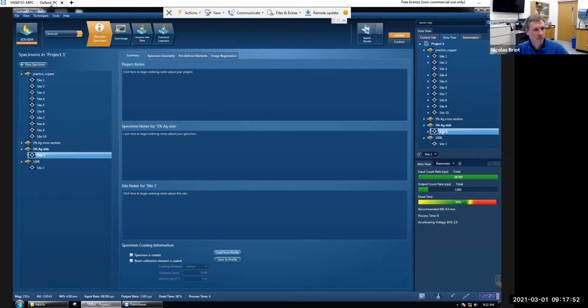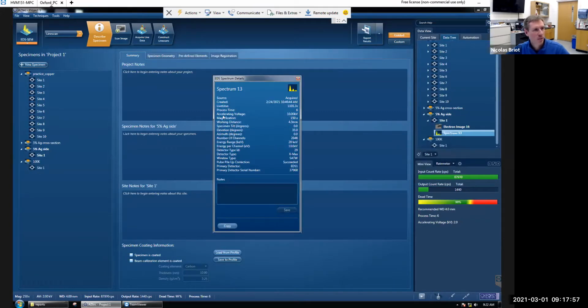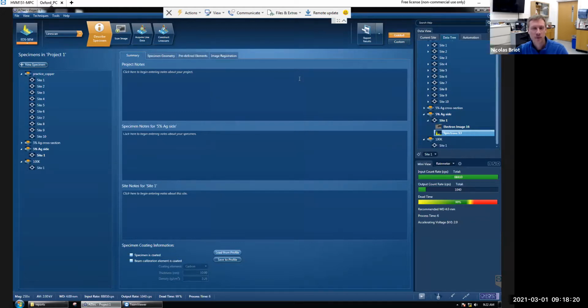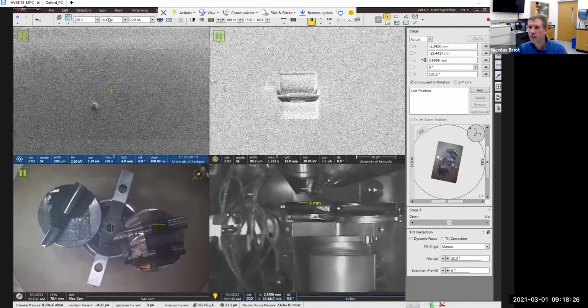So last week, what we did, and I can check the details of that spectrum, we used an accelerating voltage of 10 kilovolts. Okay, so remember, we have to have the energy of the incident electrons high enough that it can excite the X-rays we're trying to see, right? So silver has some X-rays at about 3 keV. So we want the accelerating voltage to be about 2.5 times more. So that's why 10 kV was a good choice. So we're going to do the same thing, which means I'm going to go back to the microscope and go from 2 to 10 here.